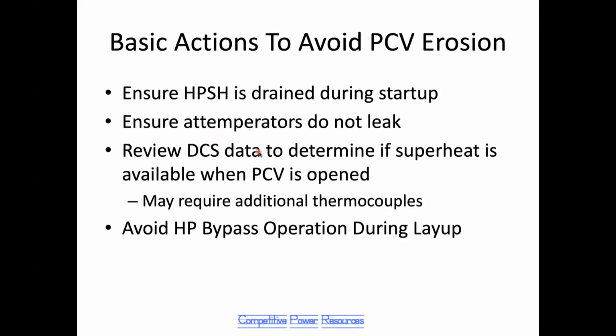You'll need to review some DCS data looking at these upstream and downstream thermocouples on your HP steam pipe to determine when you have superheat and when it is safe to open the bypass. In some cases, it may require you adding some additional thermocouples to look at pipe temperature locations that aren't in your normal instrumentation. Now, if you add thermocouples like that, I'm not suggesting you add a thermal well into the pipe. I'm suggesting that you spot weld just thermocouple wire, much like the post-weld heat treat people do, onto the outside surface of the pipe.